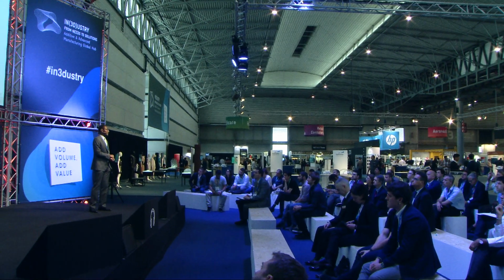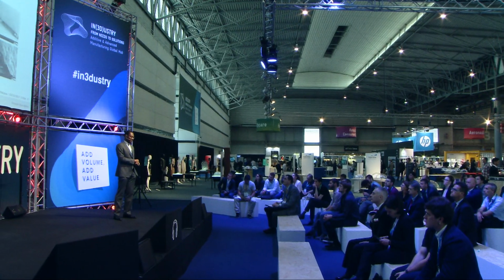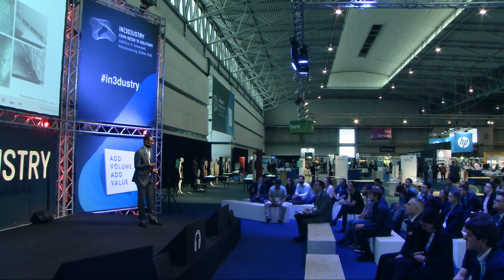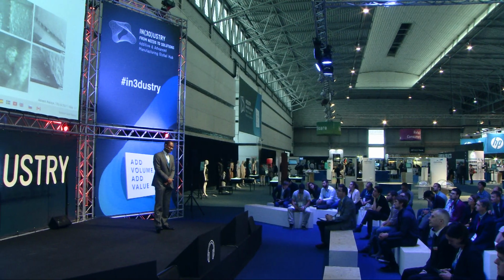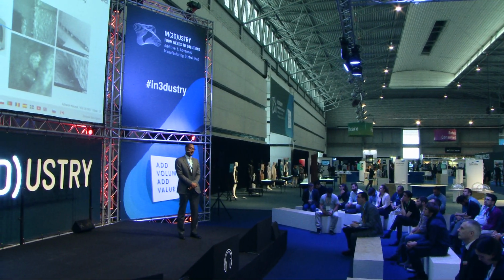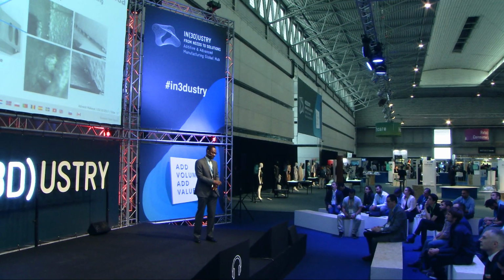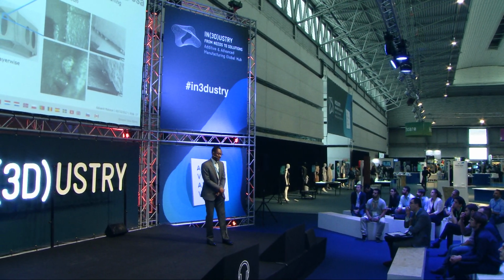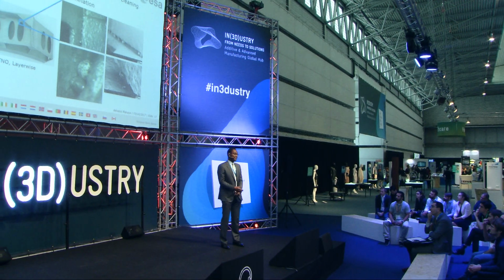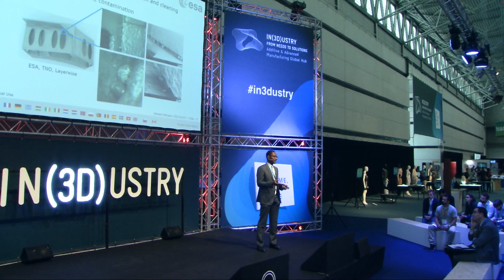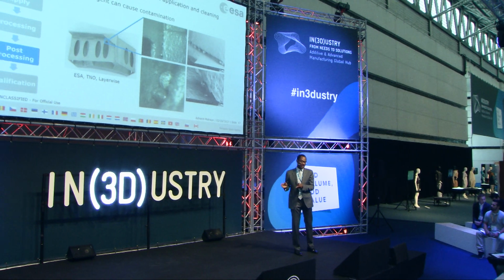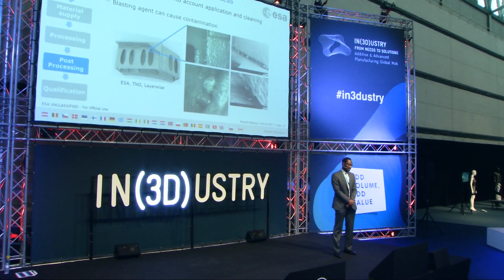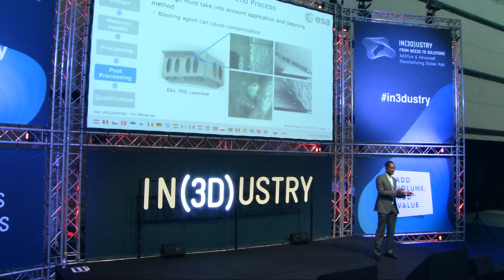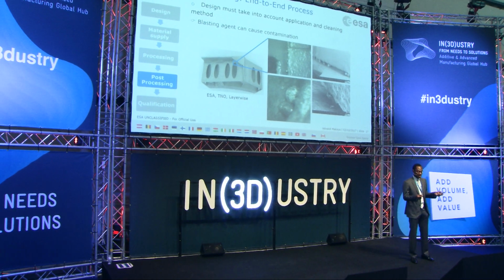In terms of post-processing, you also have potential defects caused by the agents that you use for cleaning the parts, which can get stuck in cavities in your part. In this case, you have a ceramic ball and a steel ball, which were used to peen the surface of the part, which ended up being in the part. So you have to design your part thinking about the different steps that will be needed to arrive at the final part. So thinking, if I have a cavity in this part, will it affect the possibility of trapping some peening balls and so on?